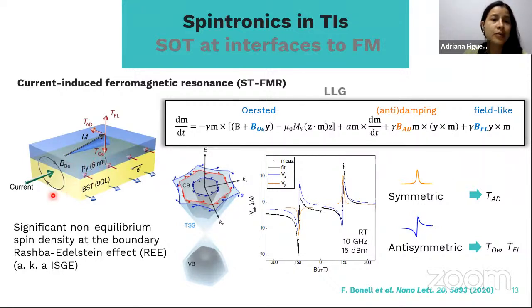When we grow these samples of the TI BST with the permalloy, we're interested in studying what happens at this interface in terms of the spin transport in this stack. For that, we use a technique called spin torque ferromagnetic resonance, which is a current-induced ferromagnetic resonance. We pass a current through this stack, and because of a significant non-equilibrium spin density at the boundary between the TI and the permalloy, we have such spin accumulation at the interface that it creates a torque.